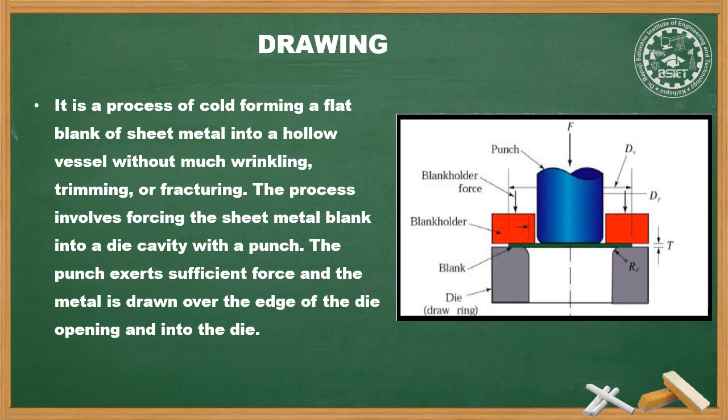When drawing deeper cups, with height greater than half of the diameter, the chances of excessive wrinkle formation at the edges of the blank increase. To prevent this, a blank holder is normally placed. As the drawing process proceeds, the blank holder stops the blank from increasing in thickness beyond a limit and allows the metal to flow radially. The limiting thickness is controlled by the gap between the die and the blank holder, or by the spring pressure in case of a spring loaded blank holder.